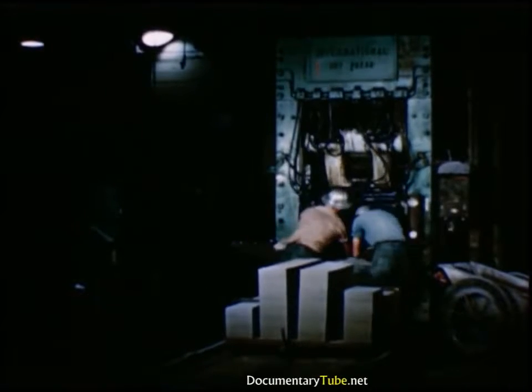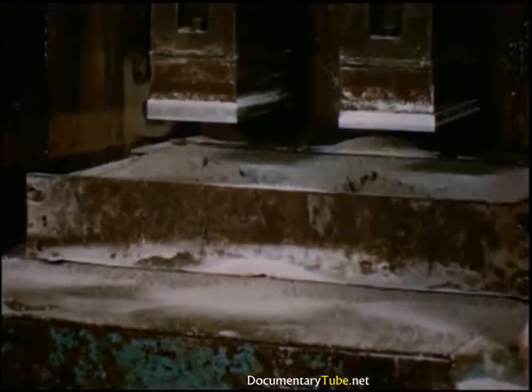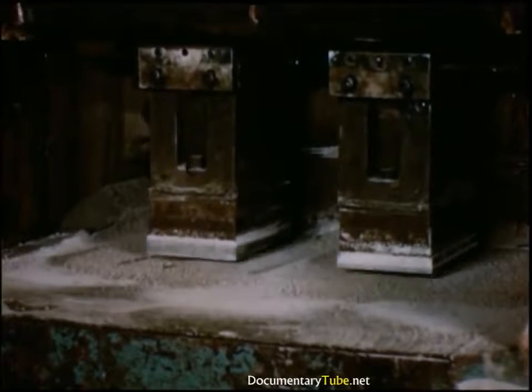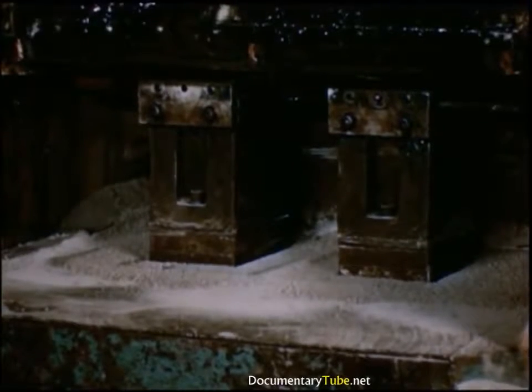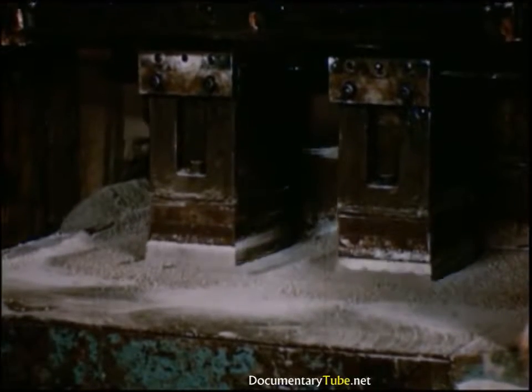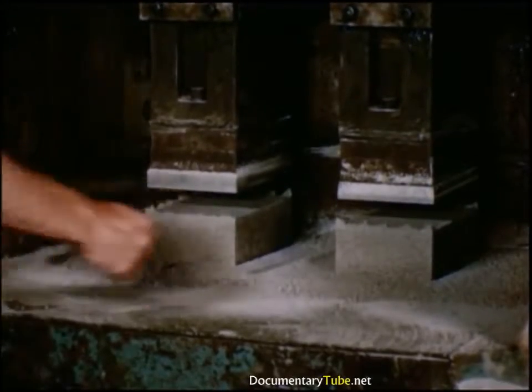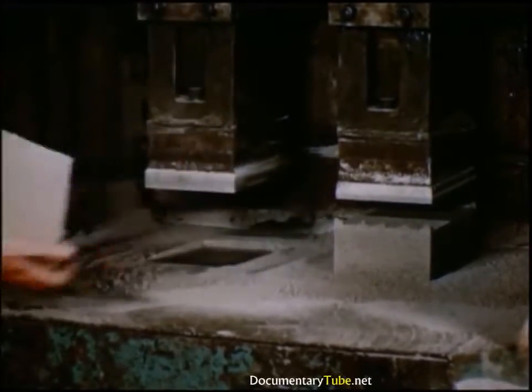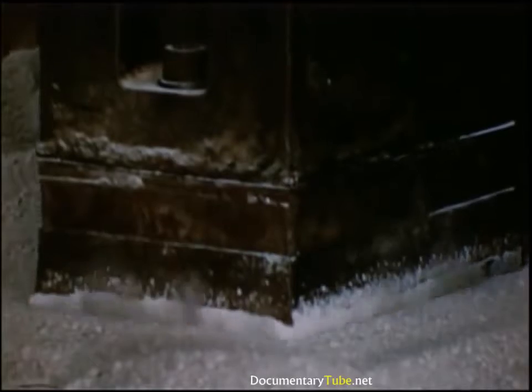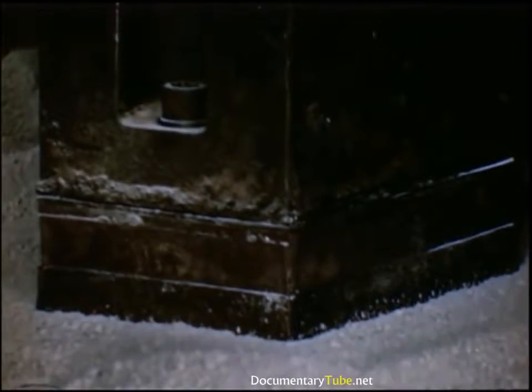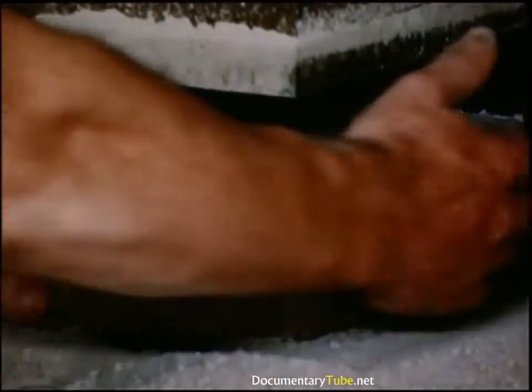Shape is determined by the die, and accuracy of size by the tolerances maintained. Each set of dies will press about 9,000 bricks before it is worn to the 64th of an inch tolerance permitted. Each press is capable of exerting 2 million pounds every stroke and of turning out 18,000 bricks a day. As the bricks come from the presses, they are relatively soft. The cement has not yet set.